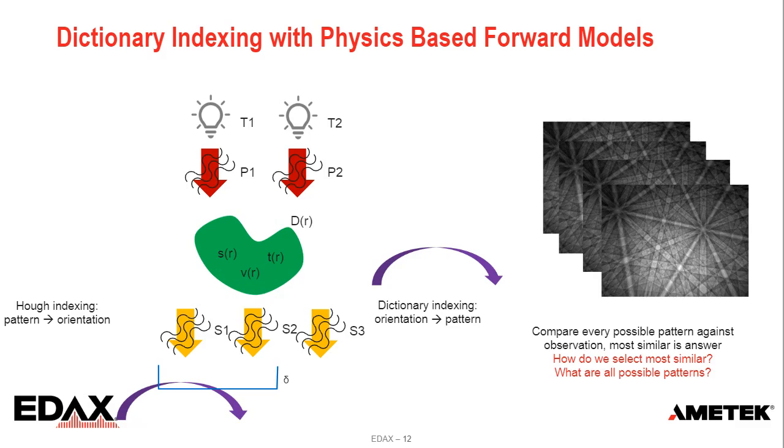And you can test that out with a purely simulated experiment. So if you have the master pattern for the cubic phase and the tetragonal phase, you can generate some simulated patterns and see how difficult these are to tell apart, and how much noise they can tolerate before I can't tell them apart.